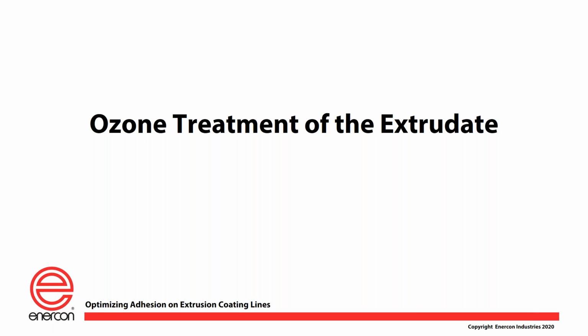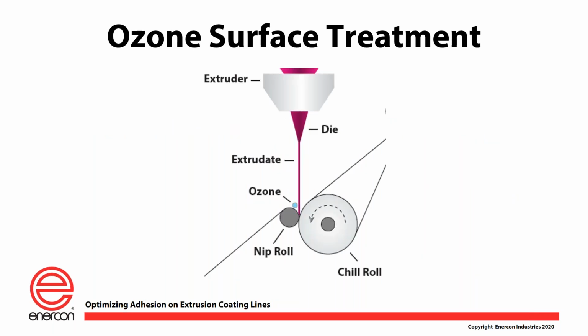So we're going to get back onto the ozone treatment of the extrudate, which is a technology that's been around for quite some time and is extraordinarily beneficial relative to getting the adhesion between the extruded material and the main web to be what you want it to be. If we do a closer view of this, on this slide you can see we have, again, our extruder, the die, and then the extrudate. And let's just say, for the sake of this dialogue, we're going to talk about the extrudate being a polyethylene material. If you look at that little interface between the nip roll and chill roll, you can see this little blue dot, which is supposed to represent an applicator for an ozone generator. That applicator spans the entire width of the die, and then it is connected to a device that actually generates ozone.